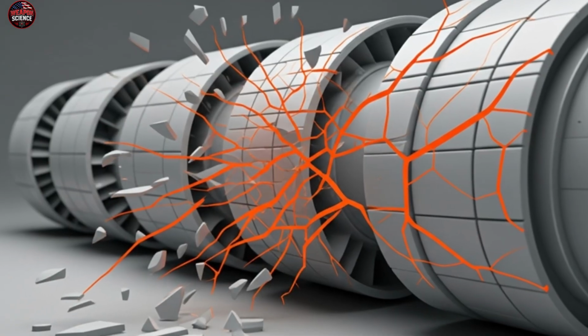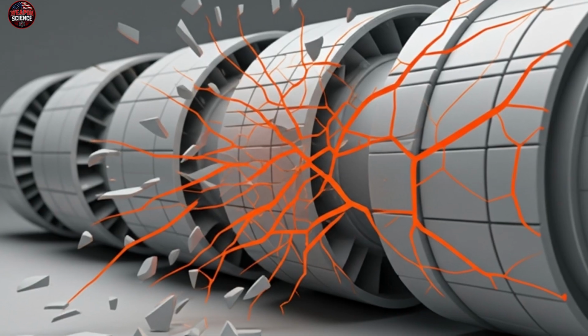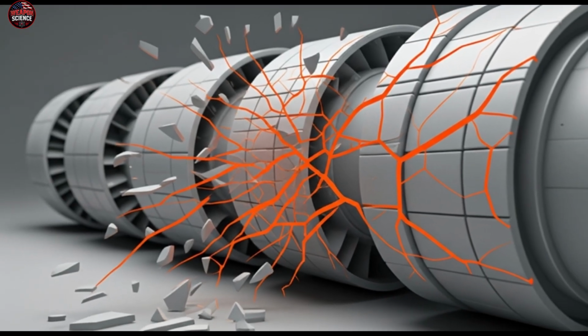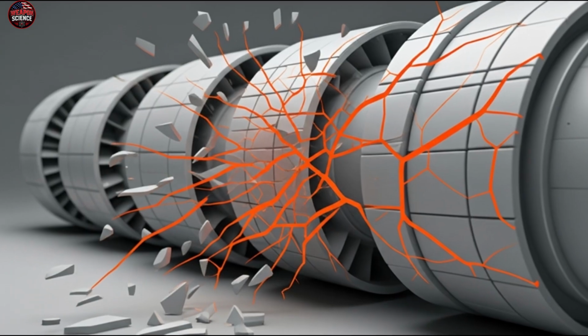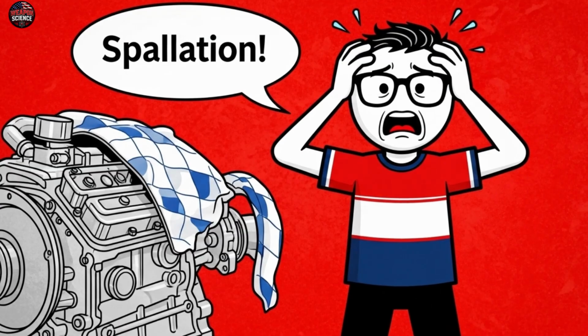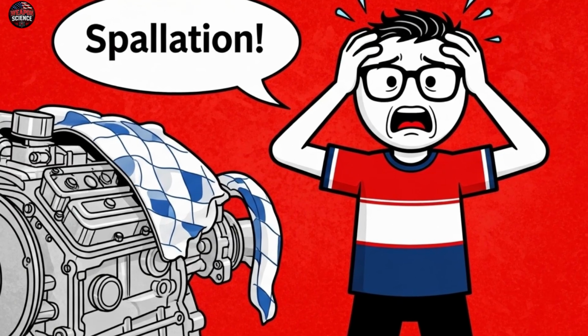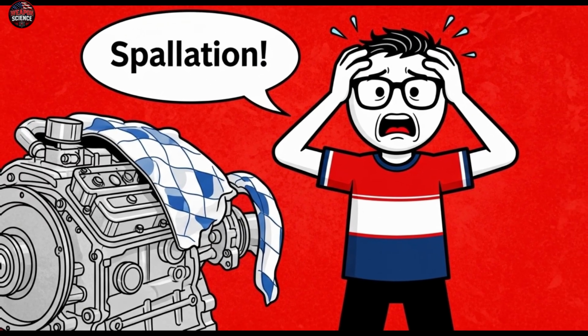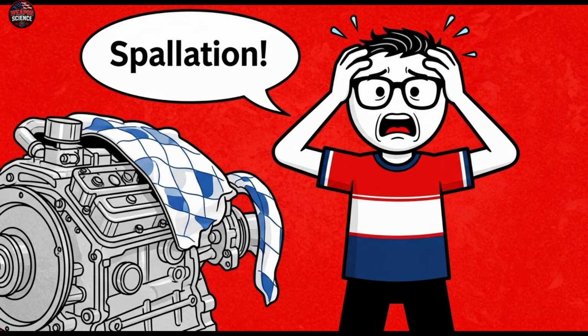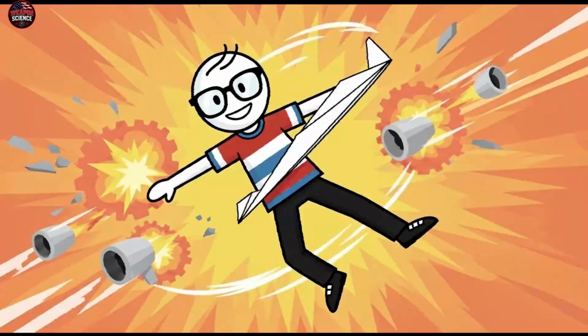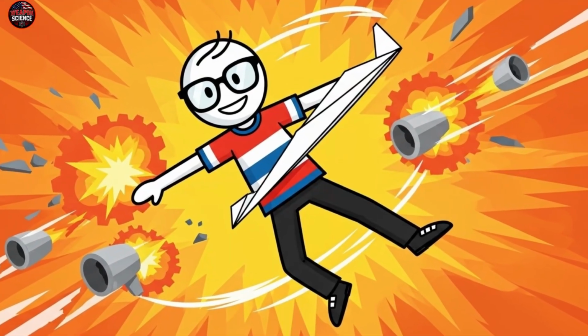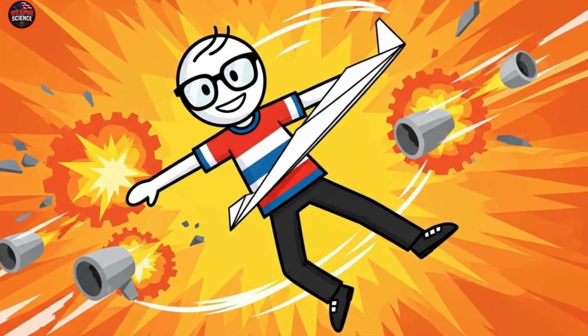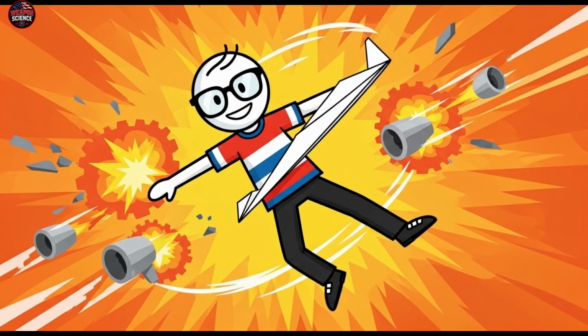Over long periods of exposure to extreme temperatures, this trapped heat causes severe thermal expansion mismatch. The ceramic coating begins to crack and flake away from the metal. This flaking, known as spallation, is an engine designer's worst nightmare. Once the coating fails, the underlying metal is instantly exposed to the full 1500-degree blast. The resulting structural failure can destroy the entire turbine stage in a fraction of a second, leading to a catastrophic loss of thrust and the potential crash of the aircraft.